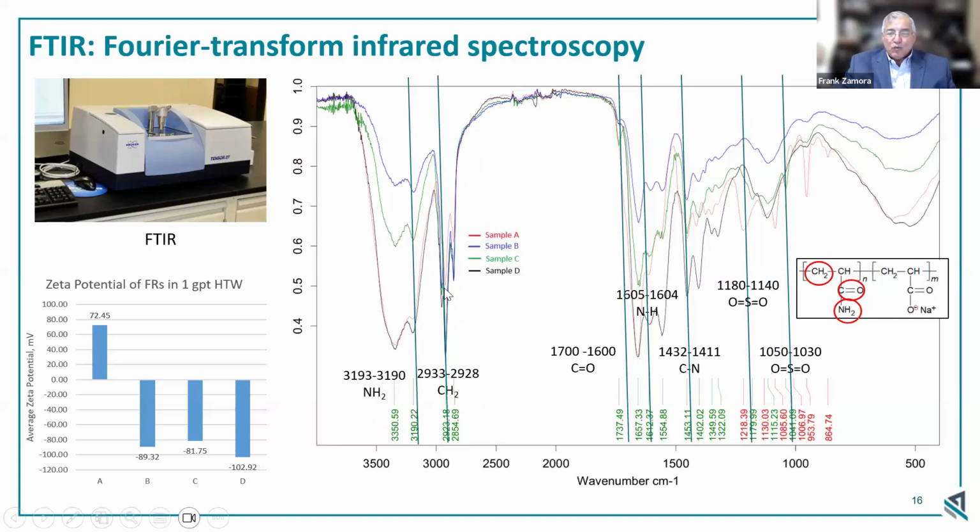So we look at that as well, but it's important to look at the NH and then to look at this carbonyl group. This carbonyl group is part of the amide structure to actually identify whether it's a polyacrylamide or not. We have the CNs, and of course, on the sulfonated AMPS one, the AMPS will have this sulfonated group over here. And this sulfonated group we can identify depending on where it is. So remember that the green one was a sulfonated one. So we're looking for this particular peak here that doesn't exist in any of the other three.